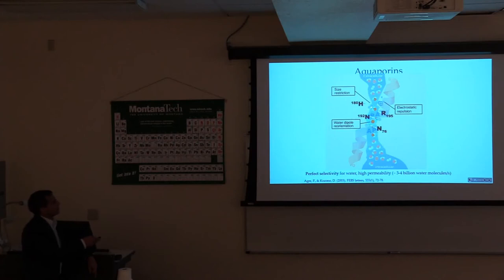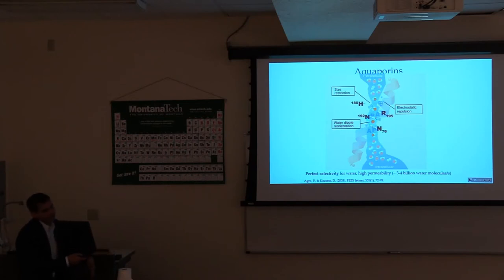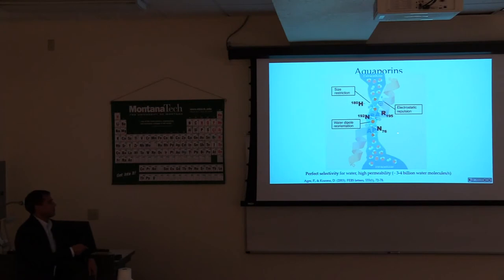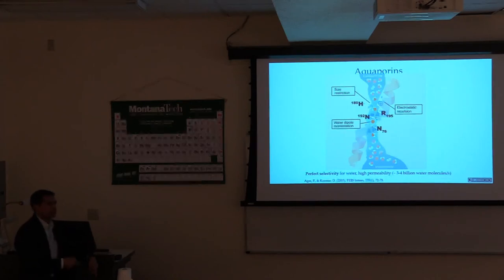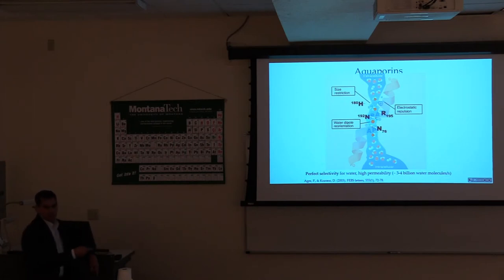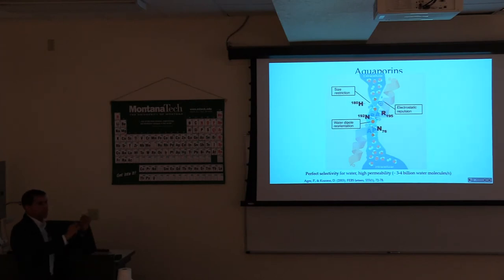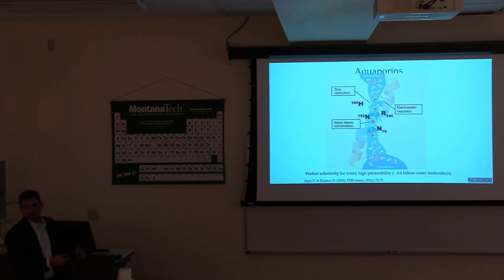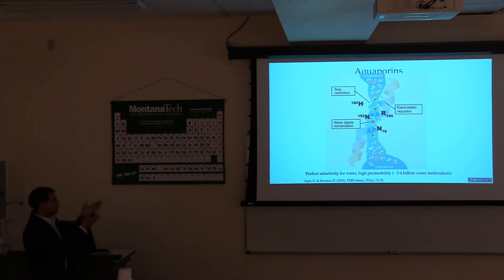The reason aquaporin is so selective is because the pore is only the size of a water molecule, so anything bigger cannot go through — no hydrated ions. It has electrostatic repulsion with a large charged residue that prevents cations. Most interestingly, there is water dipole reorientation: water hydrogen bonds to specific surface residues, which flips the dipole of water. Three specific residues bind water in different ways then flip it over, breaking the proton wire that normally allows protons to go through water columns. This prevents protons from going through, though this is overkill for desalination since we don't need to remove protons.